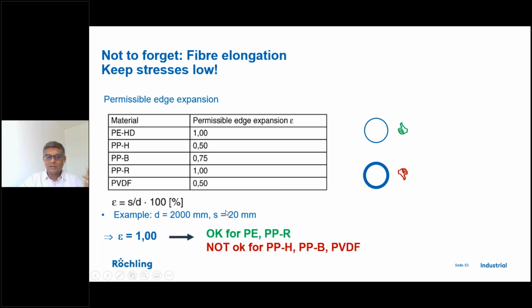You are violating the norms of edge expansion, but as I mentioned, there is a process by which you can reduce the internal stress of the sheet, and then you can roll it. But at the normal operating level, you need to follow this edge expansion. So if you have a 4-meter diameter for PPH, then you can easily roll 20 mm. But if you have a diameter less than 4 meters, say 3.4 meter or 3 meter, you can still roll it, but you have to take certain care and precaution by which you reduce the internal stress of the sheet. You make the sheet more flexible, and then you can roll it.